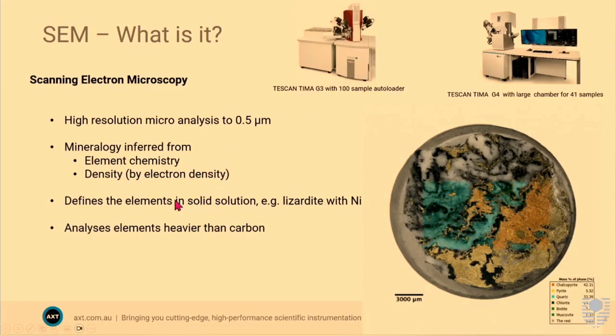The advantages are that it defines the elements in solid solution, for example nickel in lizardite. If you're processing nickel, you ideally want pentlandite or one of the nickel sulfide minerals, but you can get nickel that occurs in non-sulfide minerals, which really messes up your processes. And it can analyse elements heavier than carbon. This image you see changing is a photo of the actual sample that's been analysed, and then you've got this false colour image coming over the top with quantitative mineralogy coming out of it.